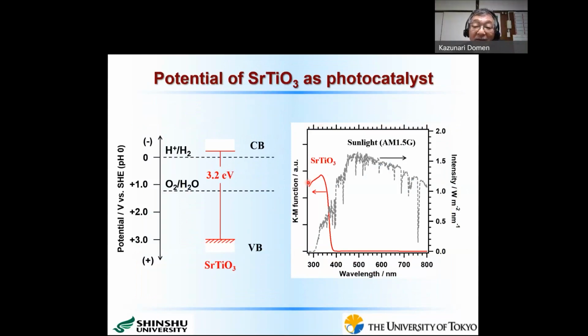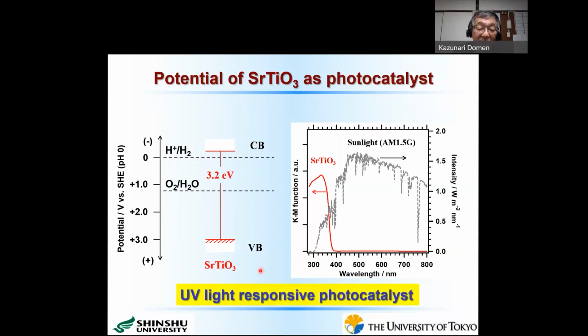But as you know, strontium titanate is a white-colored powder. So these materials can absorb only UV light, so that these materials can absorb only a small portion of sunlight. However, the band gap position of these materials is suitable to split water into hydrogen and oxygen. So this material is actually a so-called UV light responsive photocatalyst.